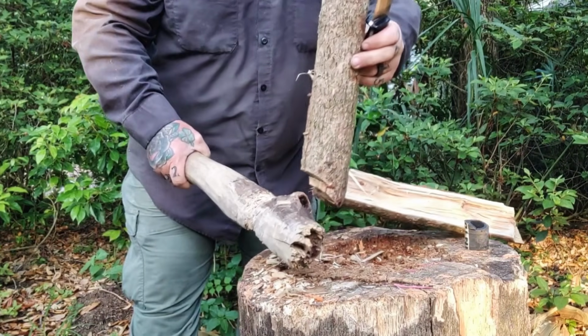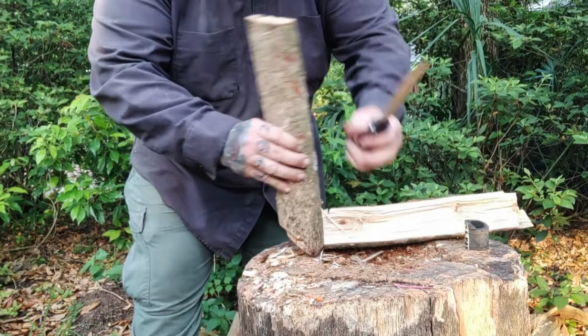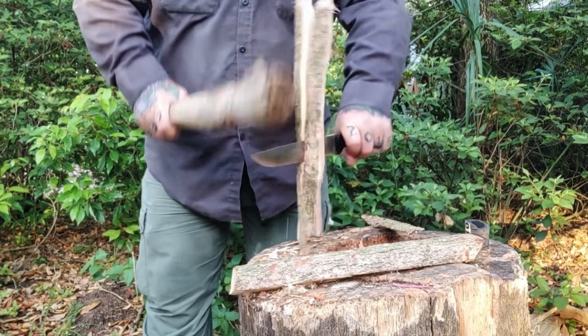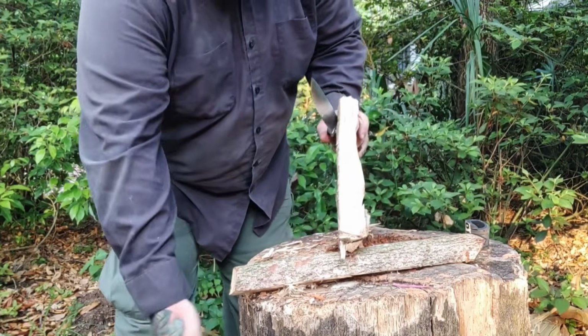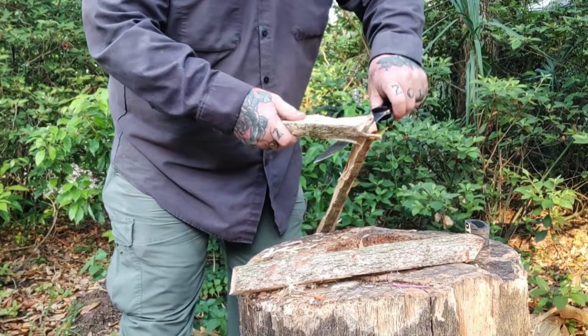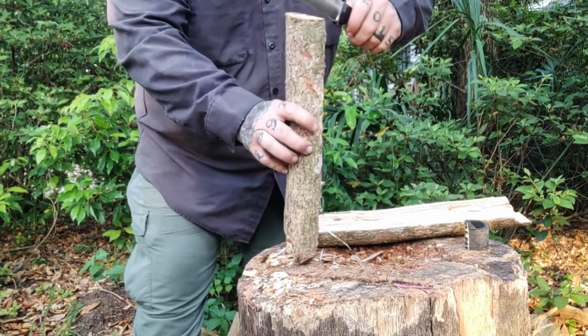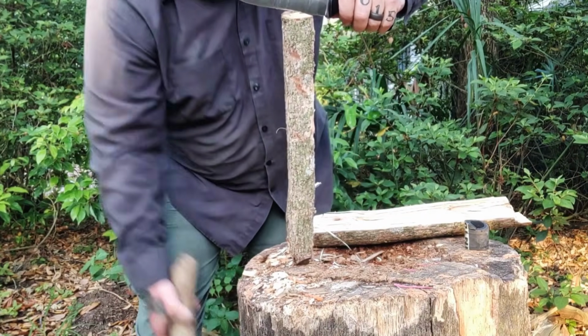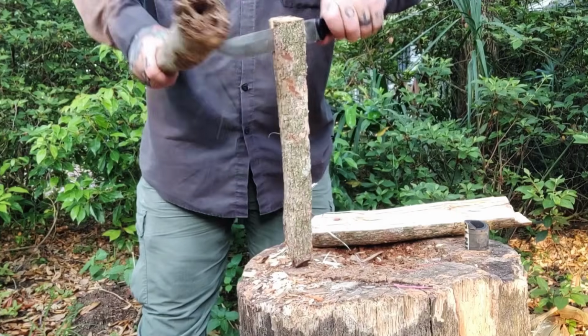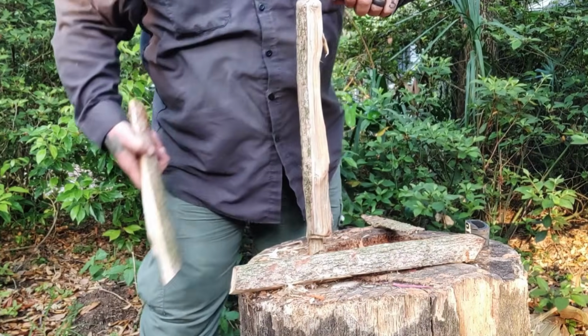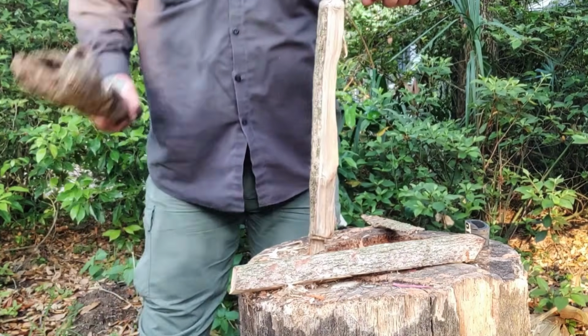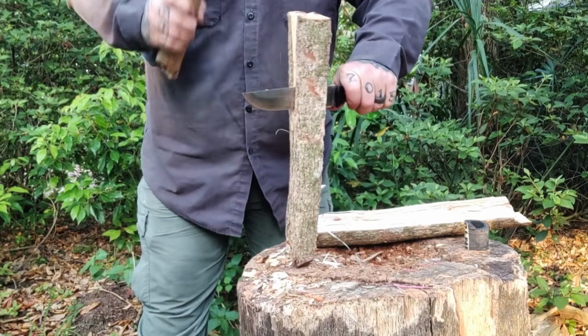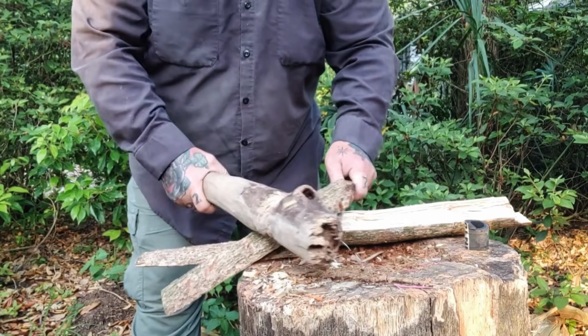72-hour saltwater test: minor surface patina development. No pitting, no functional corrosion. Battening, 40 minutes, no edge damage. Lateral stress, flex and return. Pommel hammer, zero handle movement across 40 strikes. The Bravo 2 passed every test in the sequence.